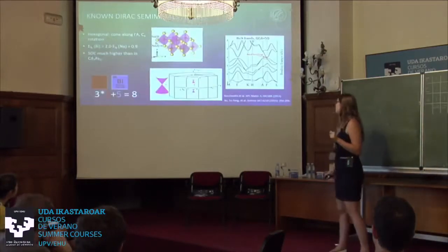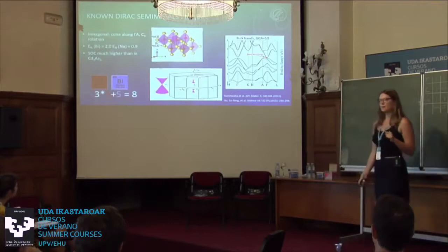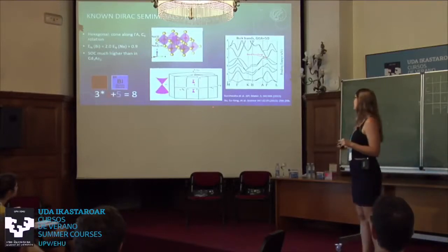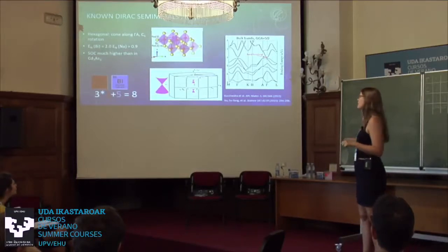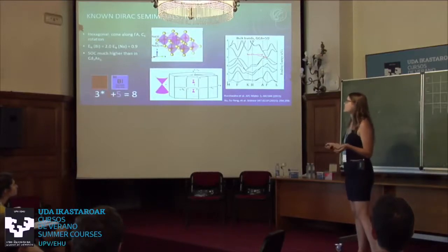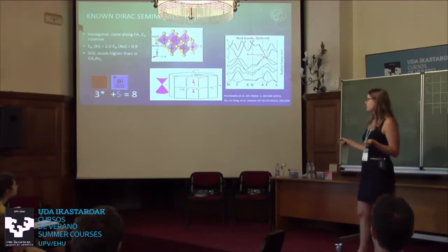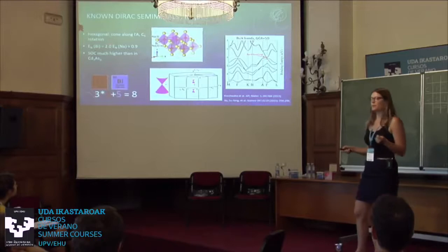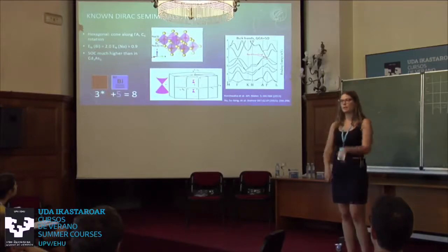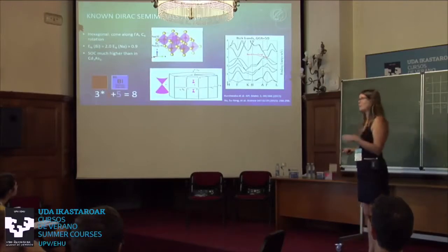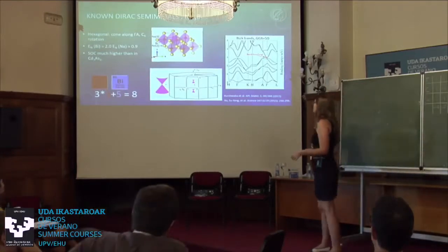So here we have sodium three bismuth. This is another really famously known 3D Dirac semimetal, and again, we have the crossing along the gamma A line, where this C6 symmetry line is. This is hexagonal and not somewhere else. We have a charge balanced material. And we have a much higher electronegativity difference than in cadmium arsenide, but therefore also much more spin-orbit coupling. So it works again. Okay, still some kind of hand-wavy, this argument.